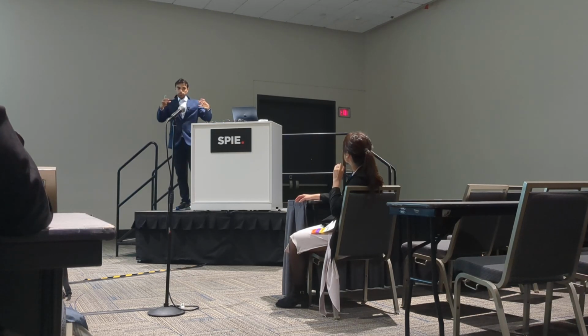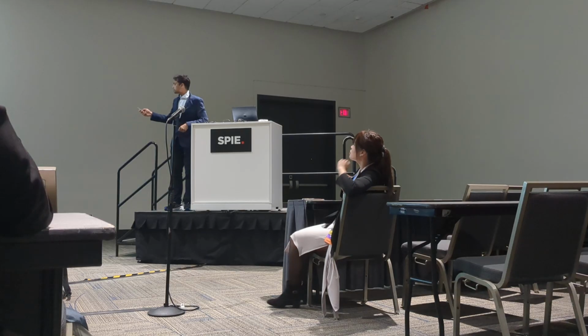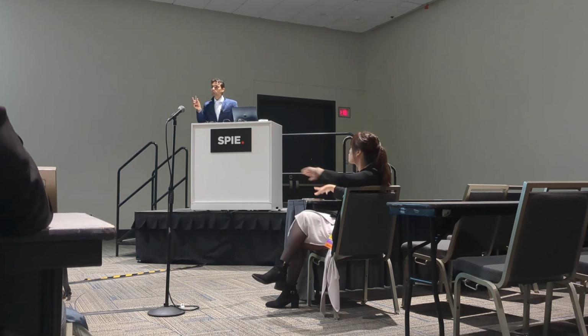But what we have in our system is a multi-particle assembly, and we can do that. From this we got the information that to simulate the droplets separating, we have to increase the interdroplet gap along the direction, and then the FDTD simulation confirms that it also shows a blue shift. So it is the plasmon hybridization which is changing in our sample, which gives rise to the color change.